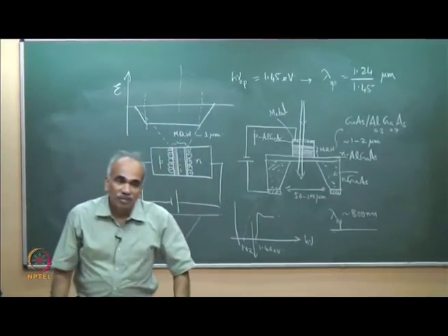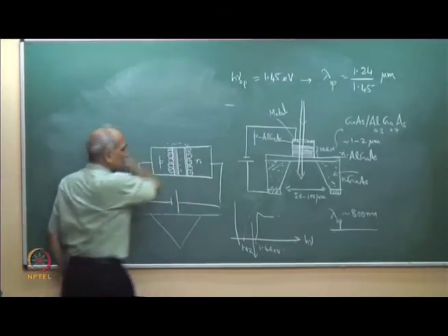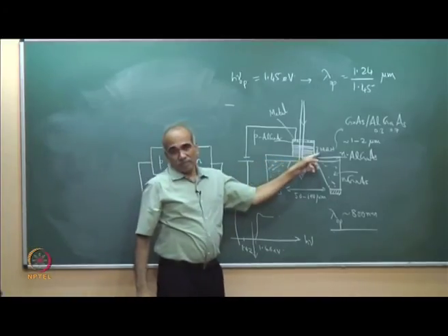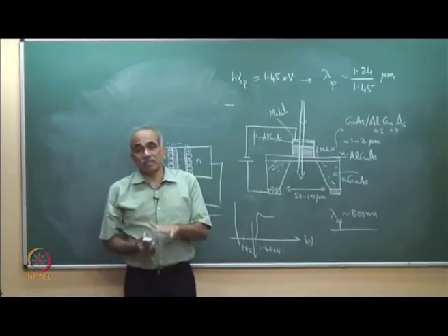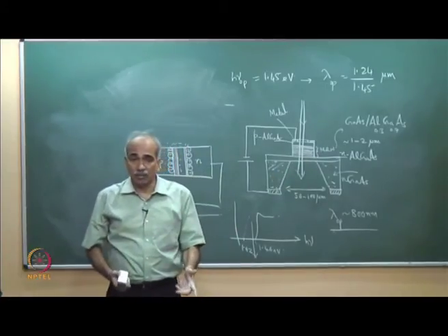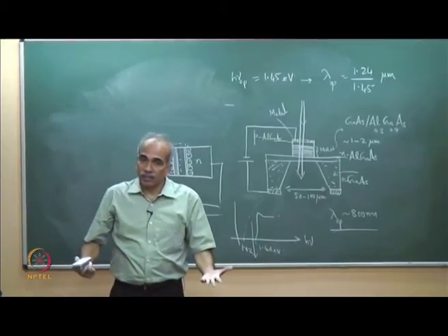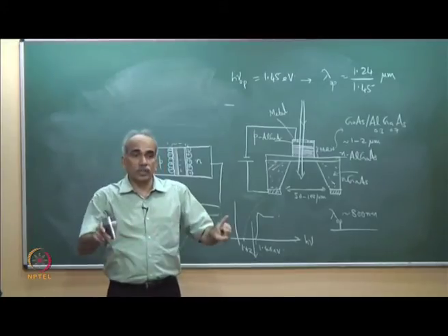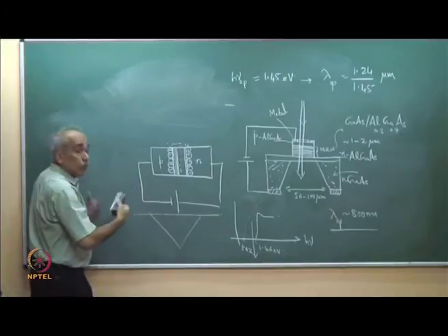But today there are better device configurations, because one of the important restrictions that we have is 1 micron, 2 micron, you have to write 100 periods. The periods have to be identical. If the periods are not identical, the energy is different, and then the effect will be different. It is not enhanced, it will start broadening, and therefore an easier and better configuration is preferred.